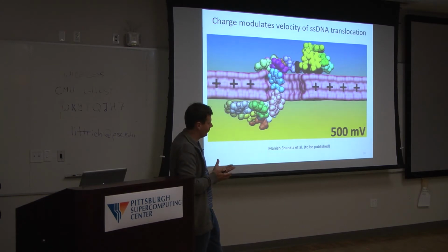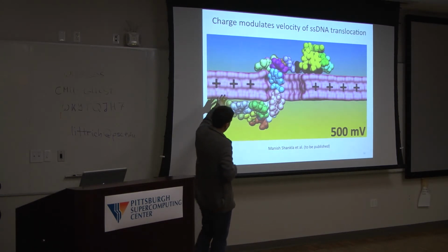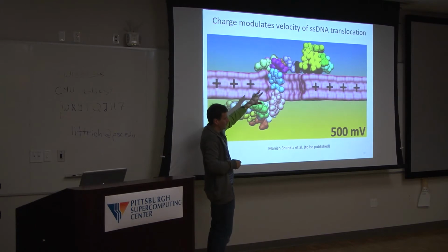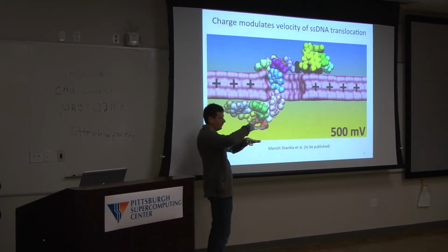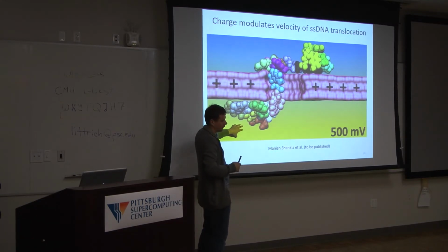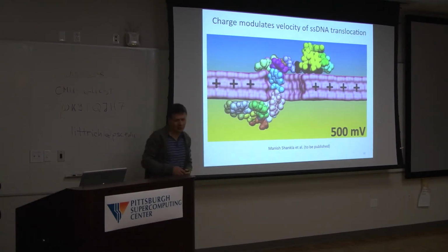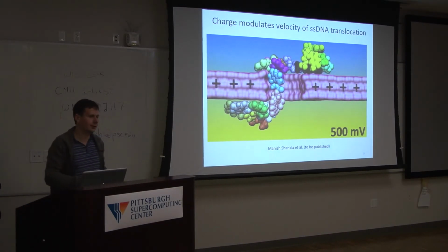But it's a particular system because you have a charge here. The DNA is also charged, but you have two other effects. One is hydrophobic interactions. So the base is hydrophobic, graphene is hydrophobic, so it sticks to it. And the final one, everything happens in 1 molar KCl. So the charge is screened. So 1 nanometer away, the DNA doesn't feel the charge anymore of the graphene. So it's this very thin layer where the charge can affect, and the particular distribution of charges at the DNA matters. So that's what happens there. Yeah?